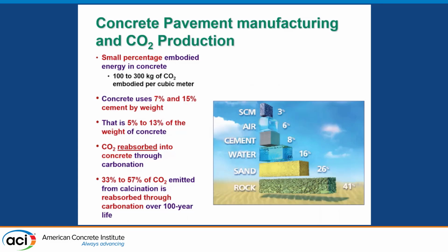Blends can be very useful, but you've always got to keep in the back of your mind that the amount of cement used in a mixture is only between 7 and 15%. And then some of that is also air content and other materials. A lot of that CO2 is reabsorbed into the concrete through carbonation. Now, there are not a lot of good studies right now that look at carbonation. The best is the Sweden study. But the materials you use will also impact that CO2 absorption. A lot of people want to bank on that statement, but when you start using SCMs, that reabsorption through carbonation is slowed at best.